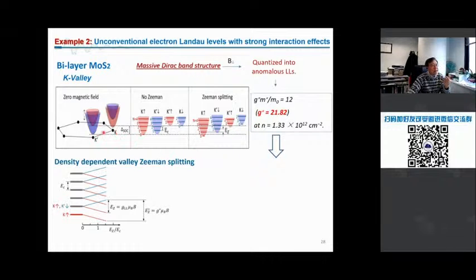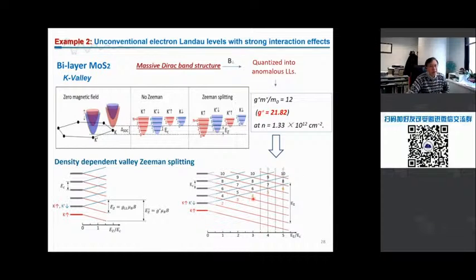So for K valleys, it's a little bit complicated compared with the previous one, the gamma valley. Gamma valley is simple. It's just 1 gamma in 1 Brillouin zone. But for K, you have K prime. So basically, there are 2 valleys with electrons occupied, but they are degenerate. They occupy the same Landau level, and you detect both. But the principle is quite similar.